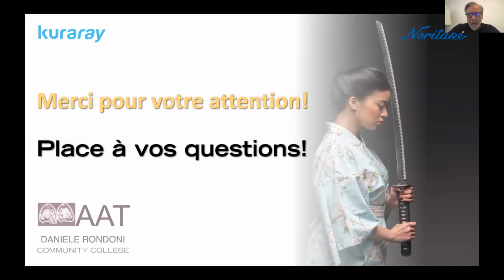This program could be damaging today with the new generation of zirconia. This kind of stabilization is an old system, an old technique, when we used the first and second generation of zirconia. But today, considering the new quality of the Katana zirconia, you don't need anything for the extra program, because normally this extra program is 200 degrees. Now it is enough to be careful regarding the perfect sintering.